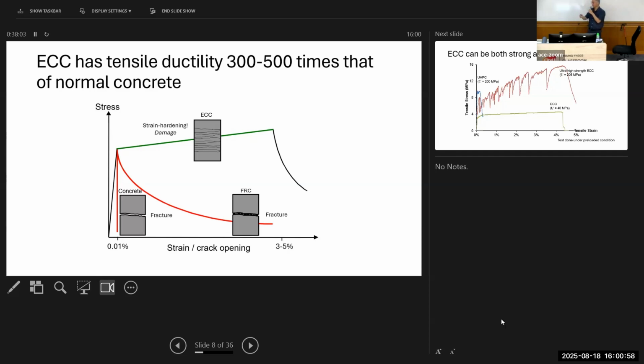And some of you, including Professor Dai, have shown that you can even push this further. And what is different from conventional concrete and FRC is that the peak point for these two materials happens at roughly 0.01%. So this tensile strain capacity, we are talking about not just 2 times or even 10 times, it's hundreds of times more. So it's truly ductile. And that's why you see that curvy face facing at you when you bend that beam. And that's what we expect our infrastructure to do when it's put into a building, for example. When that building is subjected to severe earthquake loading, you want it to deform, get damaged, but still hold the load so you have a chance to escape. You don't want that beam or column to suddenly snap into 2 parts. You have no chance, right? So that's the safety resiliency concept I was referring to a moment ago.